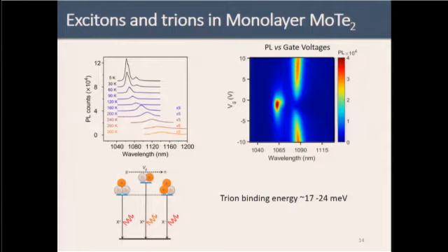Here, as you can see at room temperature, we have a kind of broad band and a small emission. As we go from room temperature to lower temperature, below 60 Kelvin, we start to see a shoulder nearby. And then as we go lower, to 5 Kelvin, this shoulder becomes very pronounced, and we think, okay, this is something. And then we started to tune the electrostatic gate.